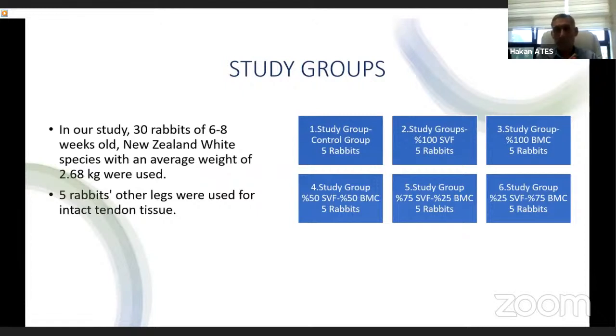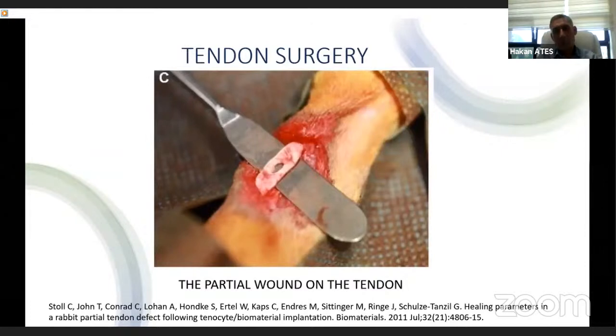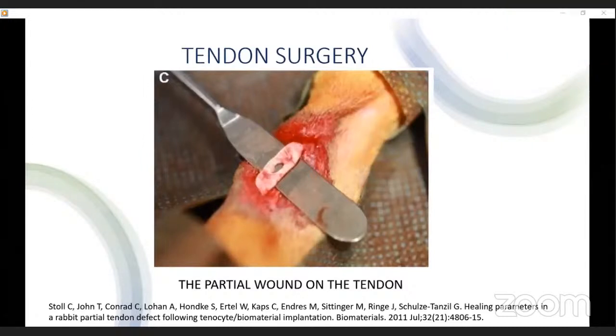There were 6 groups in our experiment, and 5 rabbits were used for each. It can be seen which concentrate was applied to which group. All surgical procedures were performed in the fully equipped operating room. After the anesthesia, partial wounds were opened except approximately 1 centimeter above the calcaneus with the help of a 0.3 centimeter biopsy punch.